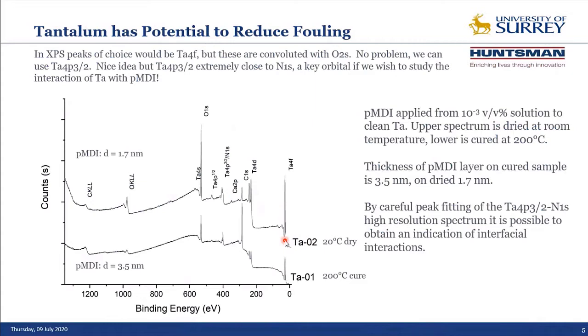So we thought, well, let's not worry about looking at the tantalum 4f. Let's look at the tantalum 4p3/2, which we duly did. And it sits exactly coincident with the nitrogen 1s spectrum. So this is in a way a good thing and in a way a bad thing, because it means that the analysis depth of the tantalum and the nitrogen information, because the electrons are of the same kinetic energy, is coming from the same depth. However, we've got to do some very, very careful peak fitting.